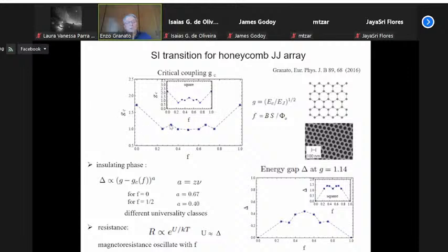The main figure here is for the honeycomb array, and for comparison we also show the square array. You see that for the square array, the next highest transition temperature is for 1/2, and then for 1/3, and so on. But for the honeycomb lattice, there is no maximum at 1/2, which is actually what you see experimentally.